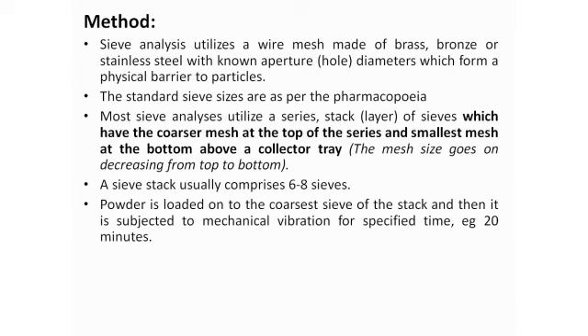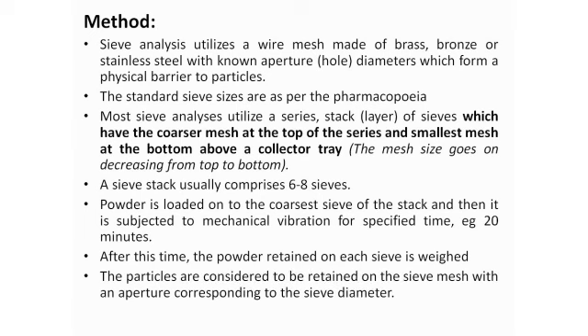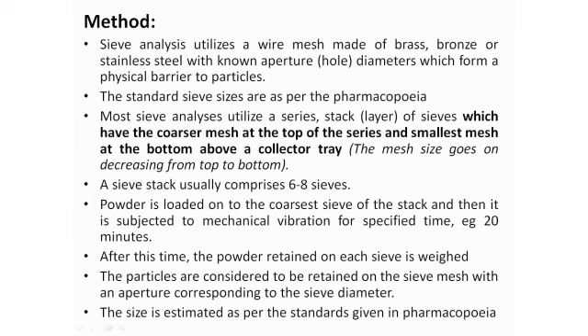The sieve stack generally contains six to eight number of sieves. The powder is loaded on the coarsest sieve at the top and it is subjected for mechanical vibration. Based on this vibration the particles escape out from this sieve. The vibration is done for 20 minutes. After this time the powder retained on each of the sieve is weighed and thus we can get the weight distribution.